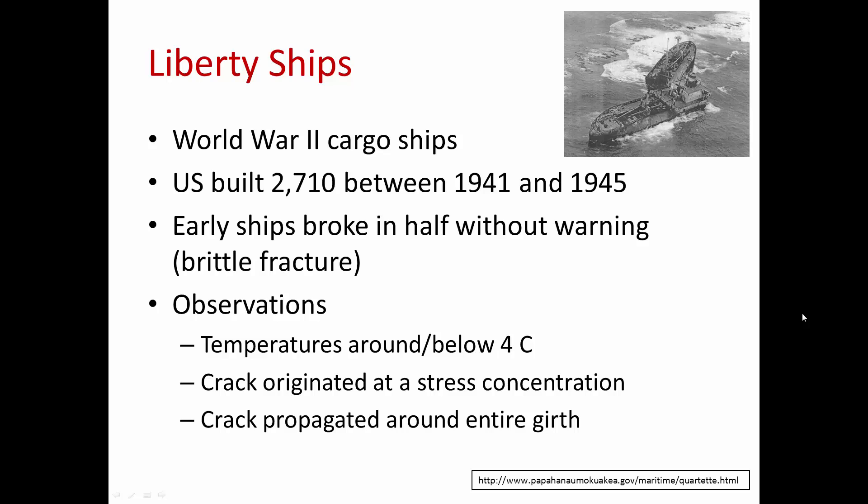In the investigation of these failures, a few things were noticed. One was that the ships tended to be in cold water, and the cracks originated at stress concentrations. There was some sharp corner or edge that initiated the crack, and once the crack initiated, it propagated around the entire girth, and the ships actually separated into two pieces, as shown in this figure.